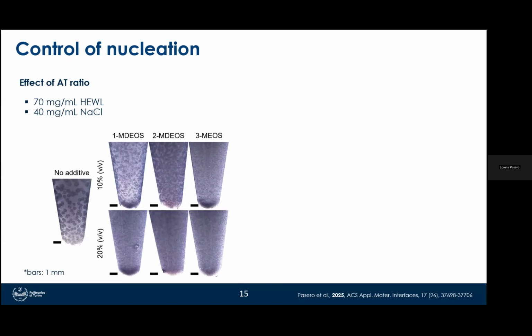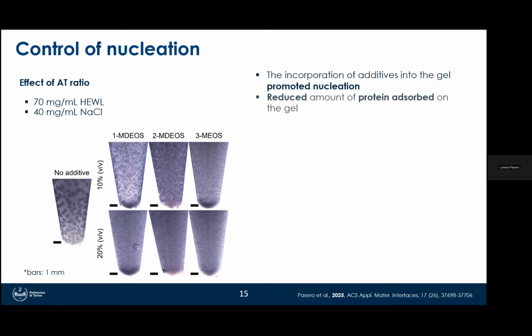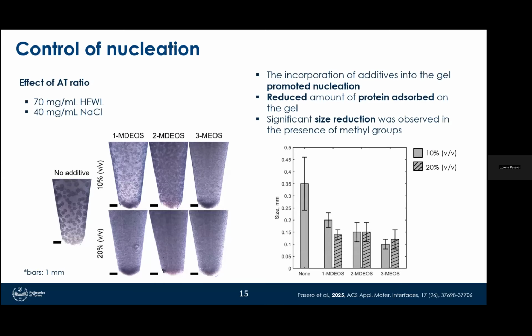And we saw that basically the incorporation of additives increased nucleation and promoted it. It also reduced the amount of protein adsorbed on the gel, and it decreased the crystal size due to the higher nucleation density. And this was coherent with the previous study in counter-diffusion. Here, the increase in the AT ratio provided a higher nucleation density for the first two methylated additives, while again a saturation effect emerged with the third additive.